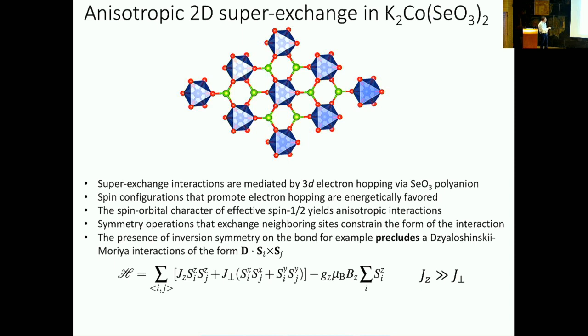And basically, you've got an interaction which is associated with the Z component of the spin-half degree of freedom, and then this transverse component, J transverse. And you've got your Zeeman term as well. And we can also estimate that Jz is going to be much larger than J transverse. So in fact, if you were to completely neglect J transverse, then you would have the Ising model. So in effect, the decoration that we need on top of what Vannimenus was doing is this transverse term, which will introduce quantum fluctuations and which will lift the degeneracy of this manifold of states that he obtained.